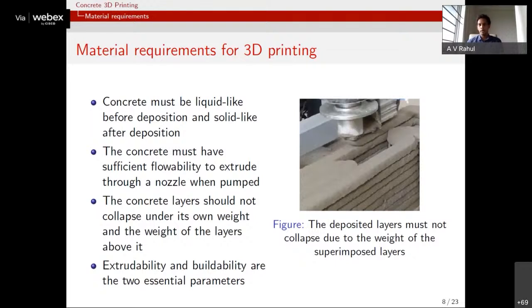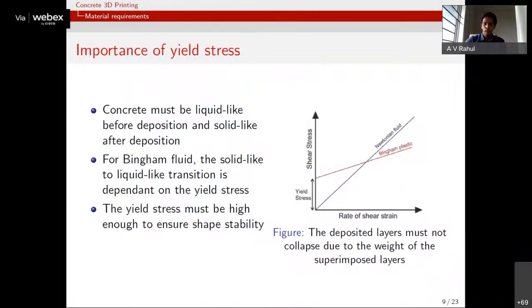So there are two aspects that you need. One, the ability of concrete to be pumped up to the nozzle, which we call extrudability in 3D printing terminology. And once it's deposited from the nozzle, it has to be able to retain its shape, or have a solid-like behavior, which we call buildability. These are two essential requirements that you need to characterize to design mixtures for concrete 3D printing.